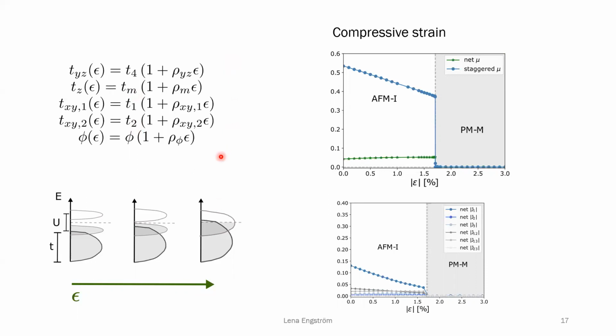We have basically 4 samples of different strain, and we are considering the general strain to be able to go both to higher values and to see what the general trend is. So we change both the hopping between different orbitals, but also this angle to be bigger or smaller. And the main effect we can see, the general trend, is that when we increase the strain, we do increase these hopping parameters T. So they become larger, which means that we have broader bands.